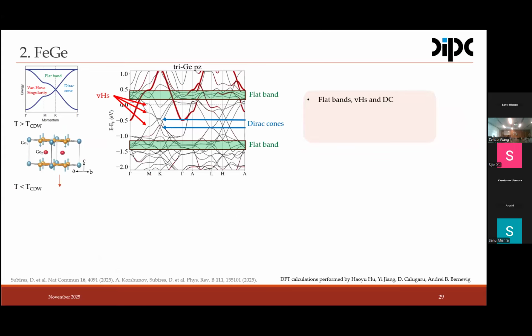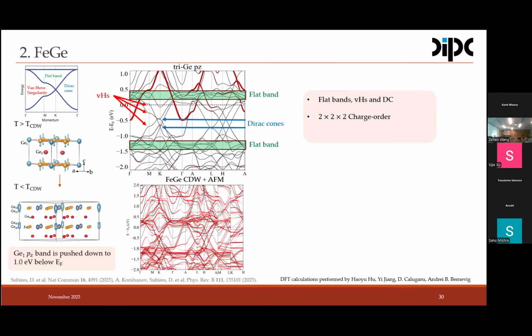If we look at the electronic band structure, we see how complex this is. Here I highlighted the p_z orbital of trigonal germanium, this electron pocket around gamma, which at low temperature, this is the calculation of the band structure of the germanium charge density wave antiferromagnetic transition. So it's actually very complex. If you want to match something here, this is very difficult, right? So the point is the band structure, both in the normal state and the charge density wave antiferromagnetic state, presents flat bands above and below the Fermi level, and van Hove singularities and Dirac crossings at the M and K points.